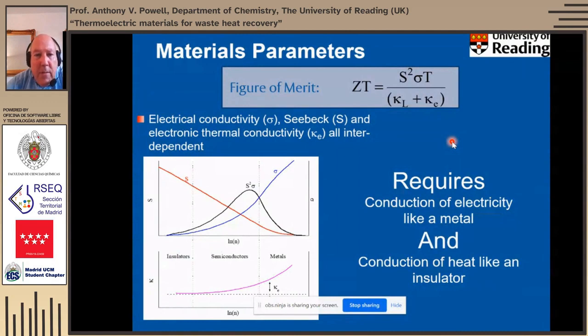The problem in terms of designing a material that has a high value of ZT is that these parameters, the Seebeck coefficient, the electrical conductivity, and the electrical part of the thermal conductivity, are all interrelated. So for instance, if we were to plot these parameters as a function of the charge carrier concentration along the x-axis, we'd find that the materials that have a very high value of the Seebeck coefficient are generally insulators or non-metallic materials with a fairly low charge carrier concentration. And of course, what that means is that they have a very low electrical conductivity. Conversely, if we go to materials which have a high electrical conductivity with a high charge carrier concentration, they've got a low Seebeck coefficient. So there's a trade-off in terms of the numerator of this expression.